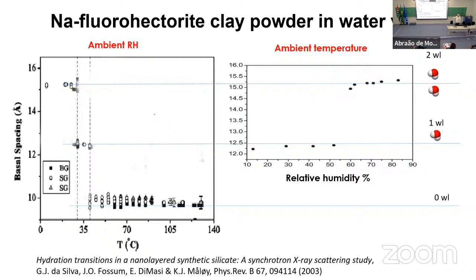You can do the same exercise by keeping the temperature constant and changing the relative humidity. At ambient temperature, you start out with one layer of water in this particular clay, and then you increase the relative humidity, still at ambient temperature, and it jumps up to about 15 angstrom. This has been studied for years by many people in different types of clays and so on.